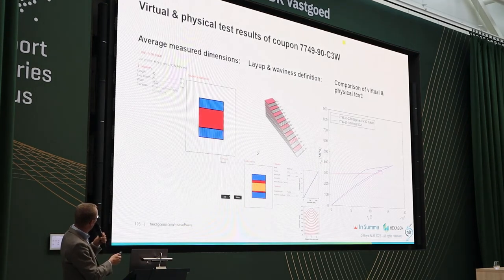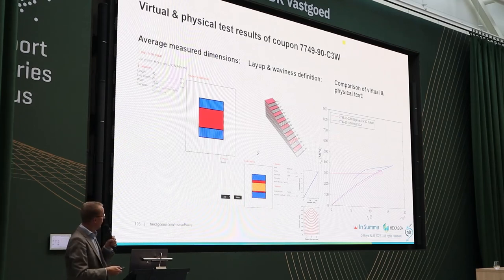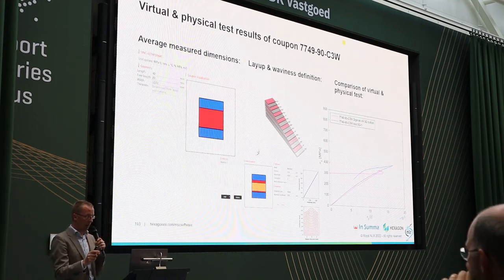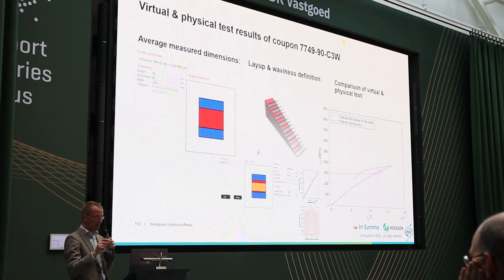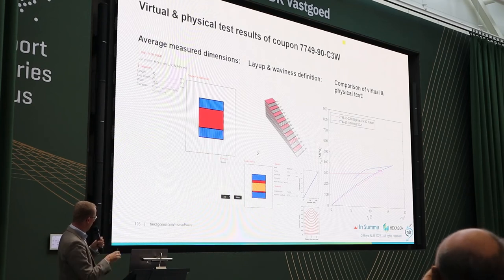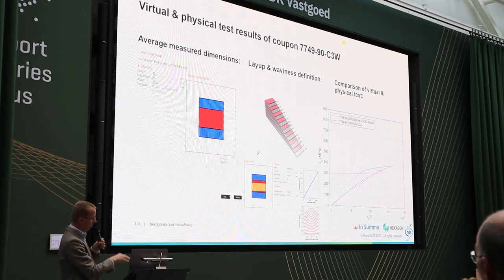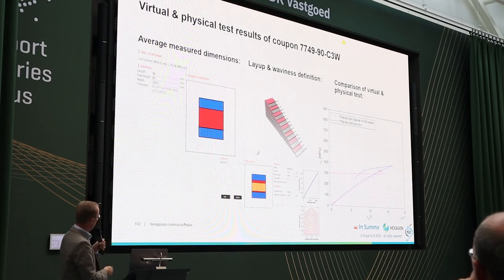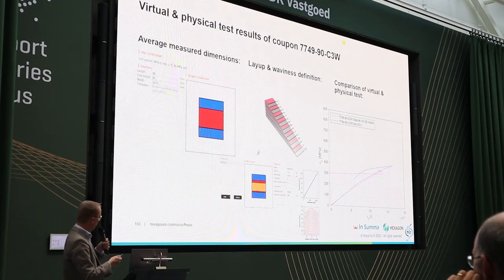Next slide. This is a coupon with fiber waviness, same orientation cut from the plates. Also, the dimensions are from real measurements of the coupon. Now I have to take into account, besides the layup, also the amplitude of the out-of-plane fiber waviness. I took that from one of the specimens that I cut from the plate, and I measured the maximum amplitude and wavelength, put that in Digimat, and used a sort of uniform decaying amplitude towards the bottom of the coupon. There are more out-of-plane waviness options. You also have user-defined waviness definitions that I didn't use yet.